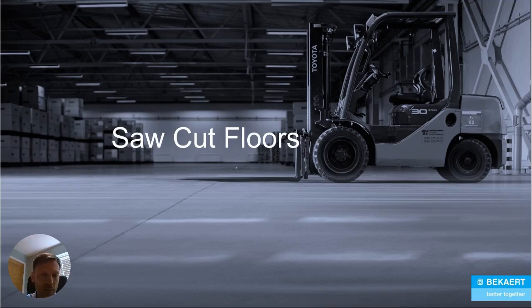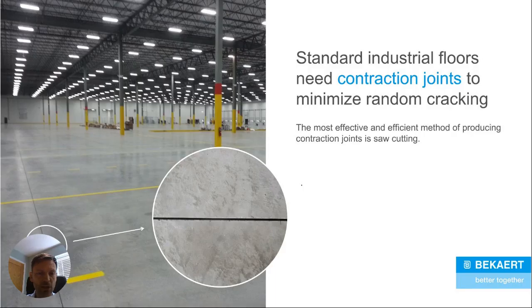So what we're going to do now is talk about different industrial floors. We'll start off with the most common ones and the oldest type of ones, which is a saw cut floor. A saw cut is effectively a planned crack in your concrete. Concrete floors have a tendency to crack if you don't have joints at regular centers. So the way to stop uncontrolled cracks is to put a planned crack in its place. So if you see a warehouse or a factory with joints at 5 or 6 meter centers, this is probably going to be a saw cut joint.